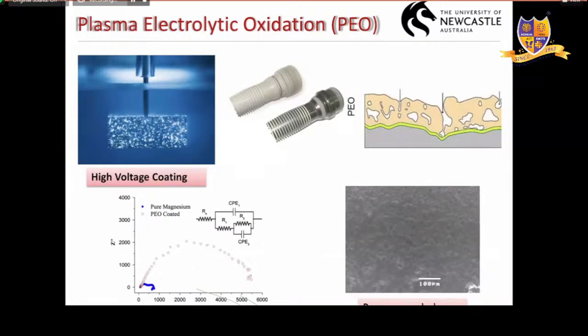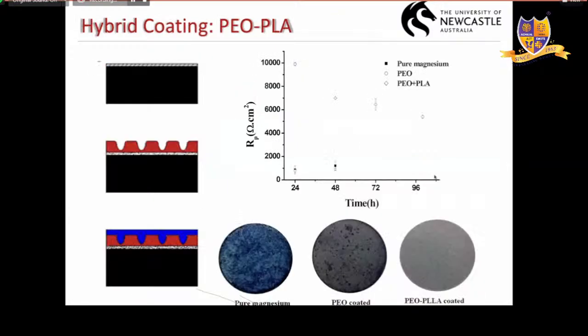The next coating we looked into is an advanced coating called a plasma electrolytic oxidation coating. I don't have much time to get into the details, but what I want to say is that this coating produces a very hard surface, but it causes a porous structure on the material. So what we did was, it forms a thin, adherent layer and a porous structure, so we seal those pores using polymers and calcium phosphates.